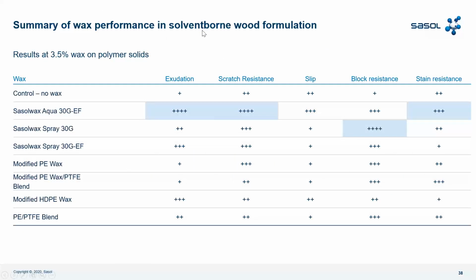So this is a summary of what I showed you. We have a solvent-based system, based on the formulation that I showed you in the slide before, which I suggest you study to see if it is similar to what you are using or not. The suggestion is that for exudation, scratch resistance, and of course slippery and stain resistance, Sasolwax Aqua 30G-EF achieves the best performance with respect to Sasol Wax and also with respect to the competition. That means the modified PE wax, the blend with a modified PE wax or with modified PE wax and PTFE, or with a simple PE and PTFE.